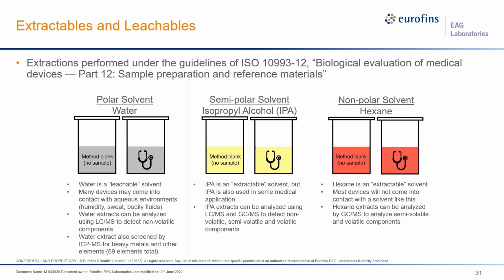If we go to our water experiment, this again is going to be a leachable situation. So this is our leachable experiment. We're going to analyze these extracts by LCMS to detect the non-volatile components which it pulls out. This is also going to be the optimal solvent for detecting heavy metals, as well as getting a full elemental screen that we will run by ICP-MS. IPA is our middle solvent, and this is going to extract a wide range of polar to non-polar components. Thus, we're going to use 2 different methods to detect what components were extracted, LCMS as well as GCMS. Finally, hexane, which is our non-polar solvent. This will extract the non-polar materials, which tend to be volatile components, so we'll analyze these using GCMS.